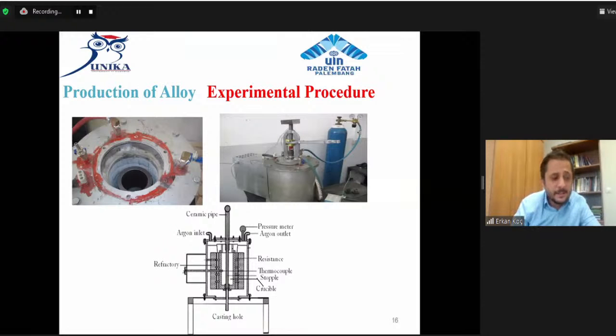The alloy was prepared by melting pure magnesium together with aluminum alloying additions in a graphite crucible under argon gas atmosphere at 750 degrees Celsius. After about 30 minutes holding and stirring, here you use a ceramic pipe, the melt was cast into a cast iron mold preheated to 250 degrees Celsius, having some diameters and some length, under protective gas. But we have to add the zinc element 1 minute before the casting, to avoid loss of zinc due to vaporization.